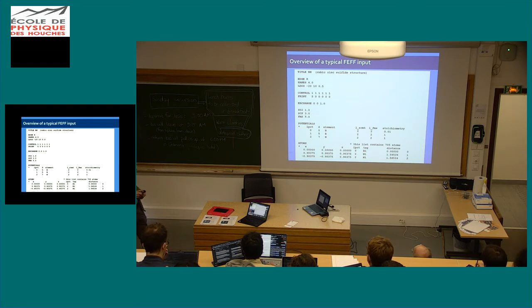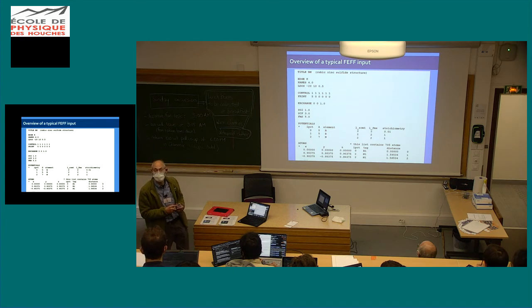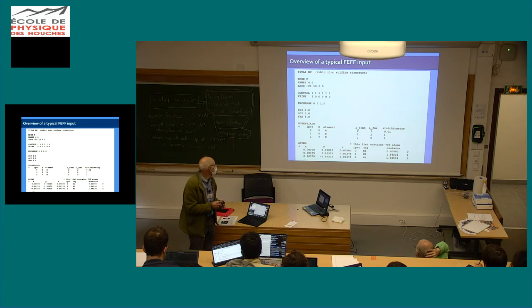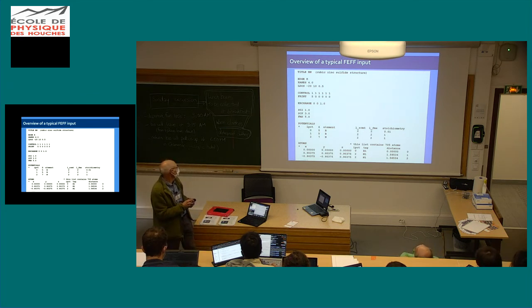Okay, the potentials in this boron nitride example: you identify the potentials by an index, a potential index. 0 is always where the core hole is supposed to be. So you would either put the 0 on the boron, if you want a boron K shell or L shell, or you would put it on the nitrogen. Here we put it on the boron. So you're getting boron, say K shell or L shell or whatever.